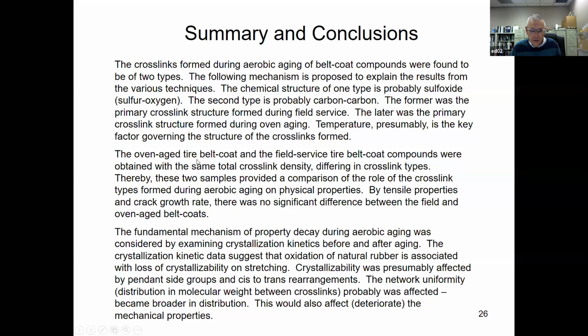that is formed. The oven-aged tire belt coat and field service tire belt coat compounds were obtained with the same total crosslink density, differing in crosslink types. Thereby, these two samples provided a comparison of the role of crosslink types formed during aerobic aging on physical properties. By tensile properties and crack growth rate, there was no significant difference between the field and oven-aged belt coat compounds. I mean, a crosslink is a crosslink. If it's a sulfoxide crosslink or a carbon-carbon crosslink, it was performing the same in terms of physical properties.